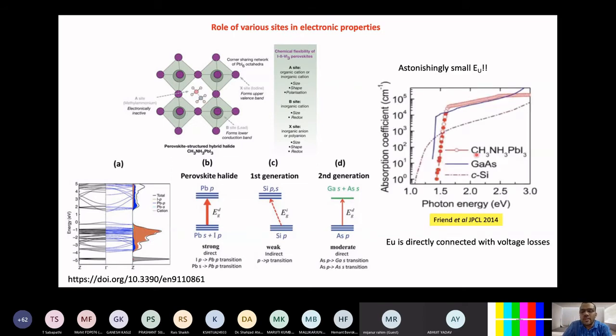And this is another very interesting observation. So gallium arsenide is the direct blue line which you see here, solid line, and you find that on the energy scale on the x-axis and the absorption coefficient on the y-axis with the log scale, your gallium arsenide has got a very steep change. That means it's a direct band gap semiconductor and it does not have any defect related tail beyond kBT, which is the case with crystalline silicon. Crystalline silicon is also very good, but you see a huge tail.